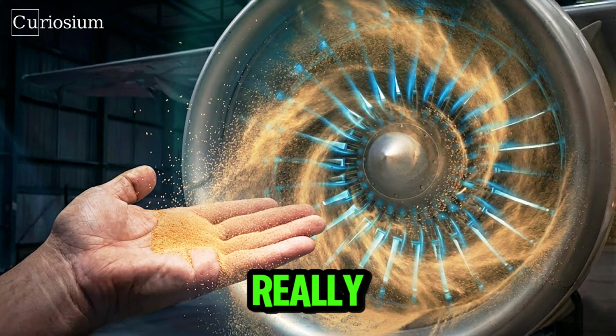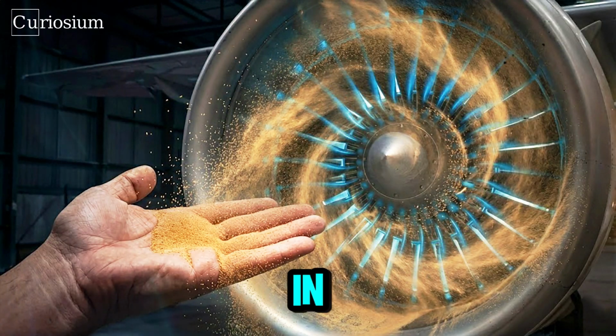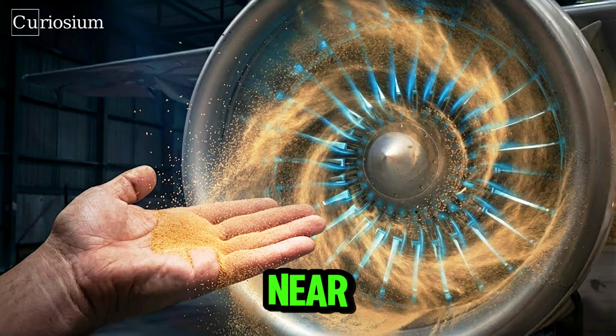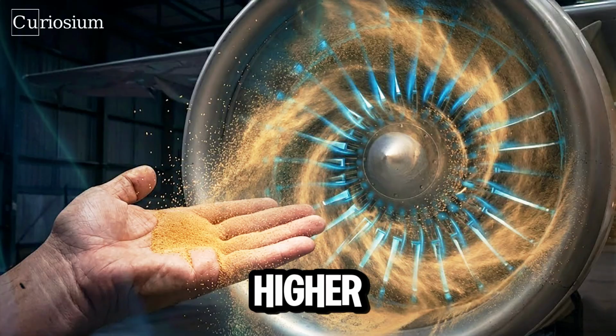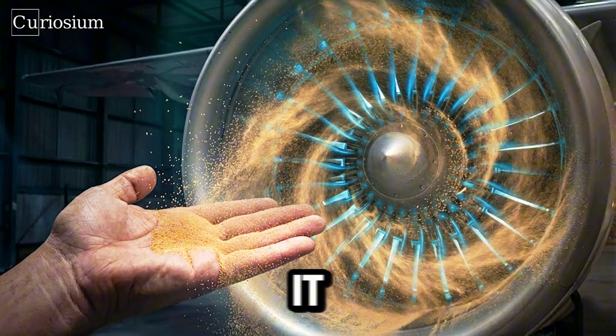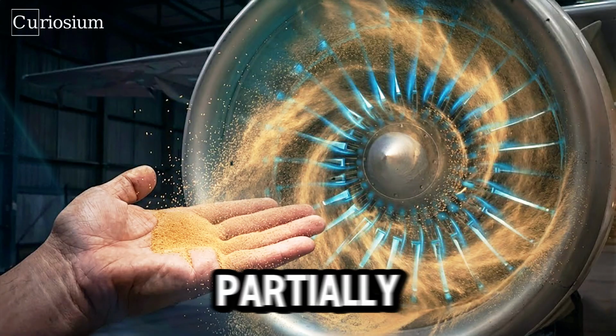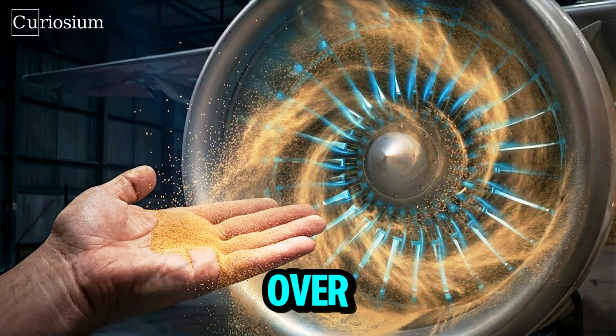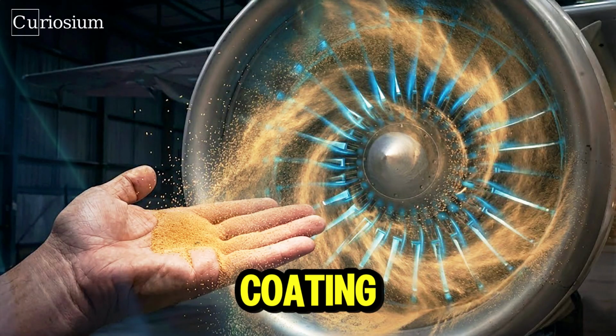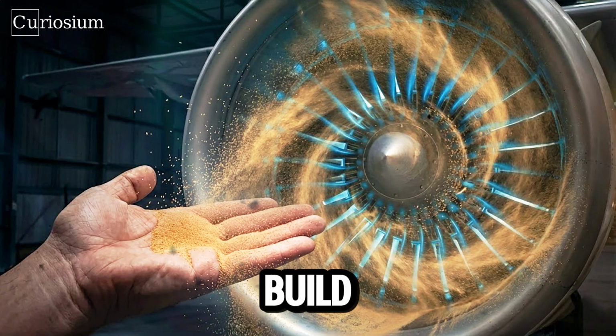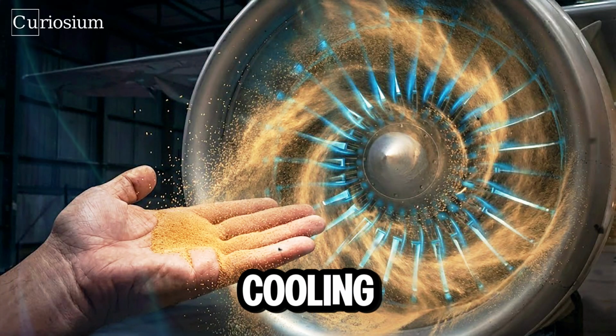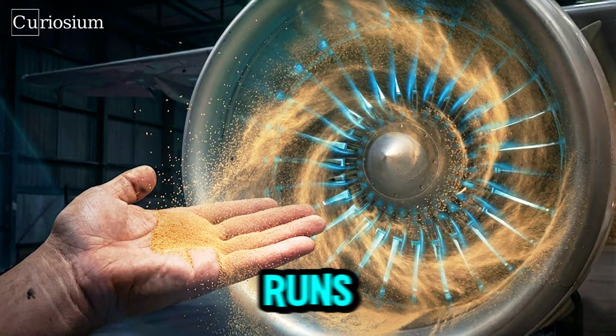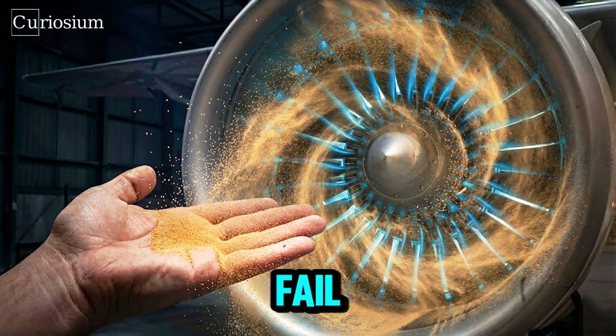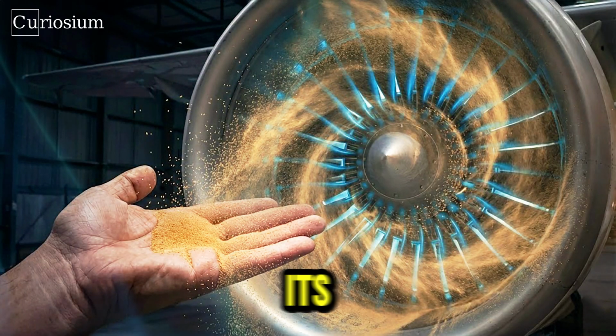What sand and dust really do inside a jet engine. In reality, even at cruising altitude, there is dust in the air. Over deserts and near volcanoes, the concentration can be much higher. When that dust goes into the engine, it does not simply pass straight through. In the hottest parts of the turbine, those tiny grains can partially melt and stick to surfaces. Over time, they can sandblast the coating, clog cooling holes, and build up glassy deposits that block the flow of cooling air. Once cooling is reduced, the metal runs hotter. The ceramic coating can start to fail, and the underlying alloy can be pushed beyond its limits.